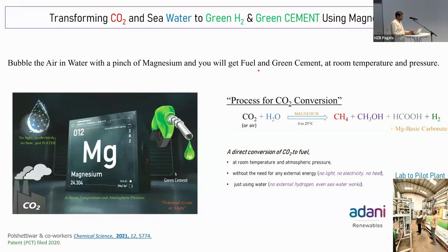In this particular work, we started with the magnesium nanoparticle, but then we realized even a magnesium bulk can react with water to get you methane, methanol, or formic acid, and hydrogen. By the way, this reaction works at room temperature. So one can ask this question, how come? I have shown you such a huge activation energy barrier, then it's just impossible for CO2 to react at room temperature. And when we saw it, we also never believed it.